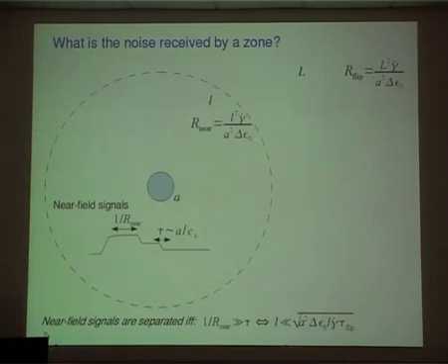So the idea is that if you strain a system faster, per unit time, you have more events. All these events emit acoustic waves. So if you look at one region in the material, the faster you strain, the higher the frequency of the noise it's receiving.